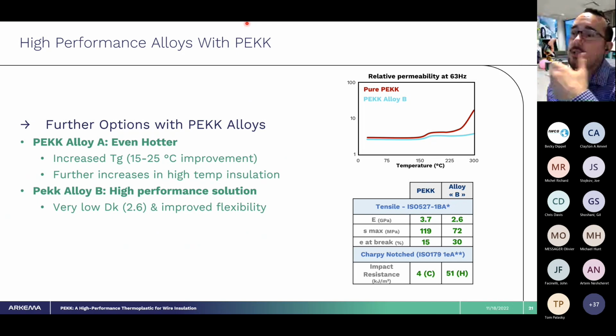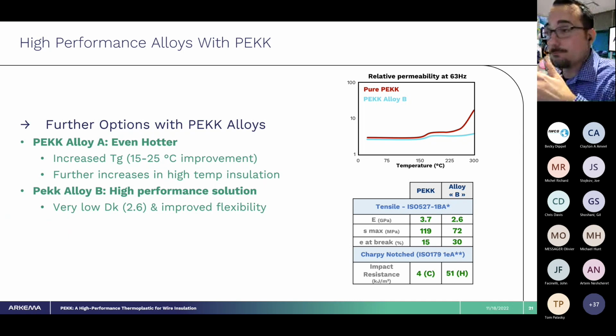The first one is a material to push the thermal properties even hotter. We've been able to show an increase of about 15 to 25 degrees C for the TG, as well as shifting out further the rise in dielectric constant as you increase temperature—so dielectric constant stays lower as temperature increases with this alloy. The second one is dropping the dielectric constant overall, even the starting dielectric constant, as well as improving the flexibility and mechanical performance of this material.